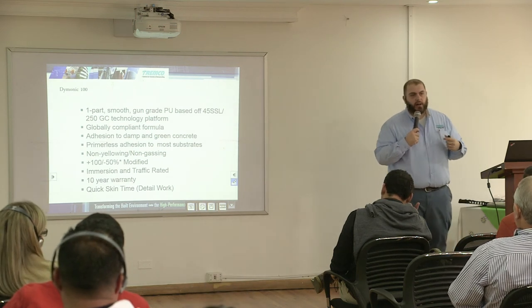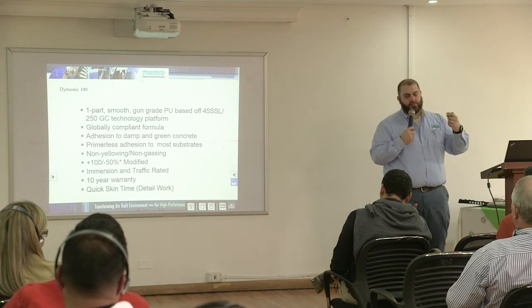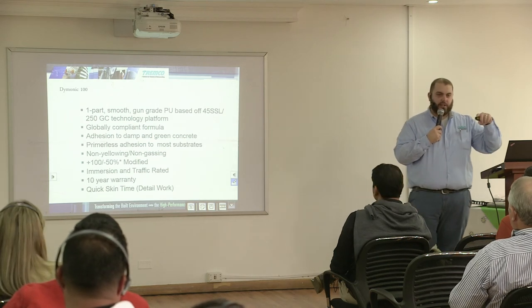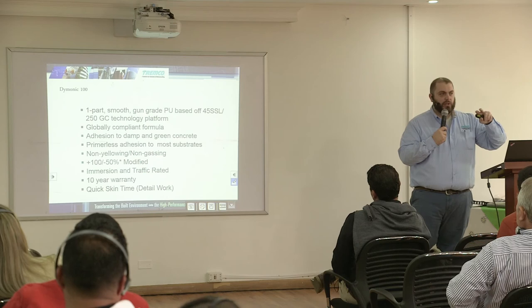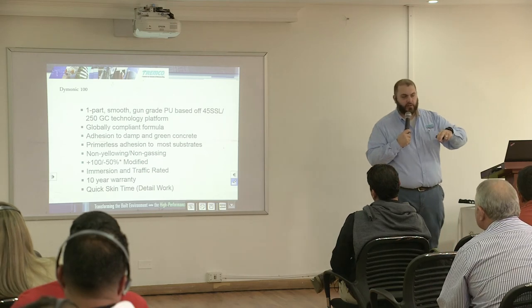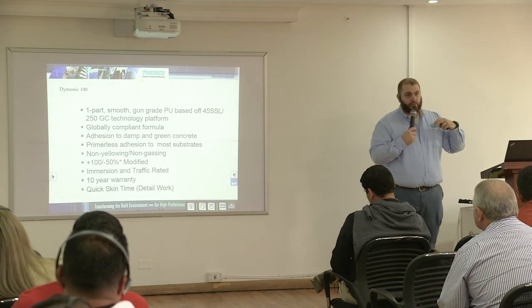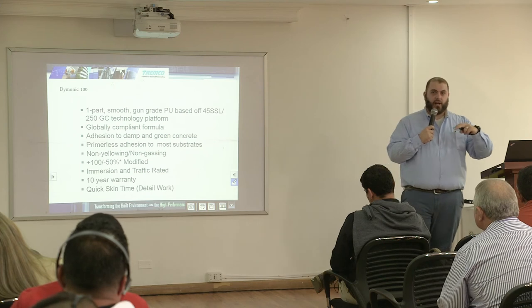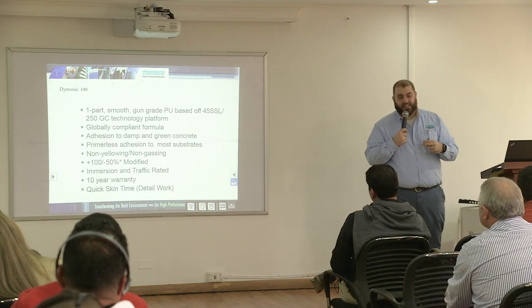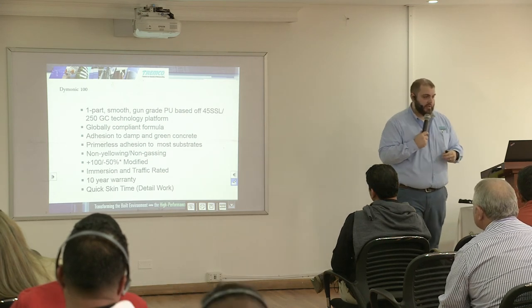The way that we buy the polymer is we buy it after the first reaction. That first reaction is what causes the outgassing, producing the CO2. We get it in-house when we make the Dymonic 100 after that reaction. So therefore, you will not see any outgassing in the field. It's also, like I said, much more UV stable because you don't have to go through that primary reaction in the field to get to the secondary reaction.